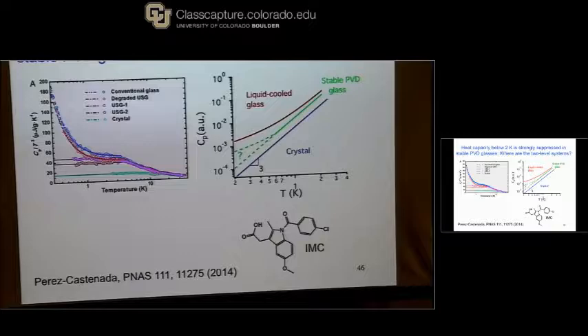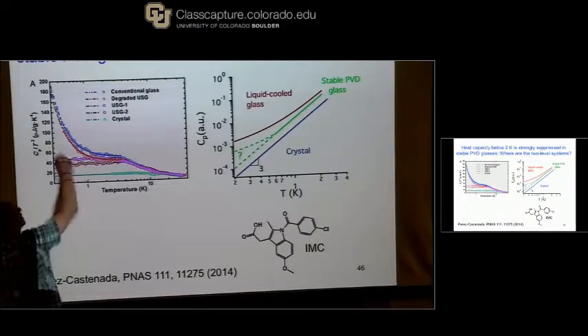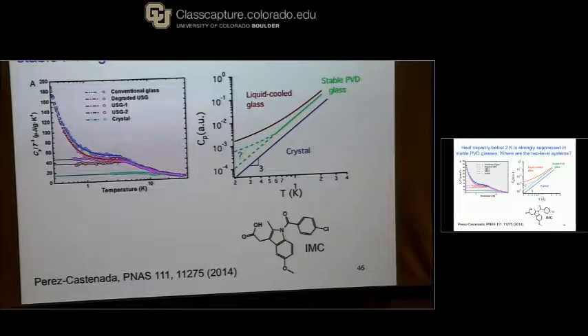Okay, so if you would insist on interpreting this data in the conventional method using two-level systems, then you would have to conclude that the density of two-level systems was either substantially lower in the vapor-deposited glass, or that the energy scale was shifted such that this uptick is going to happen at a lower temperature than's been measured yet. Okay? So I think those are two scenarios that are consistent with the experimental data. And then there may be other interpretations that don't involve two-level systems that are also consistent with the data.